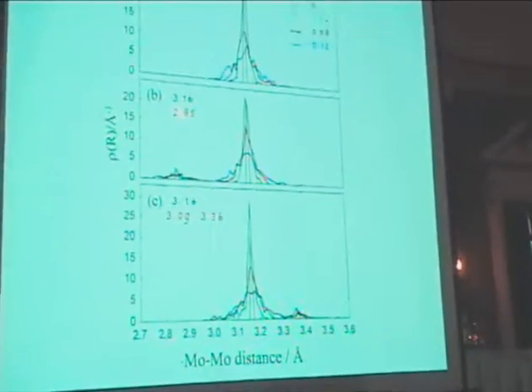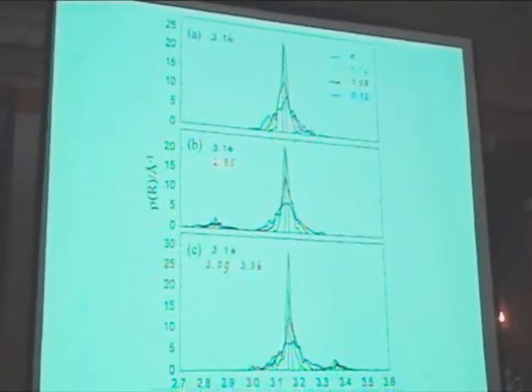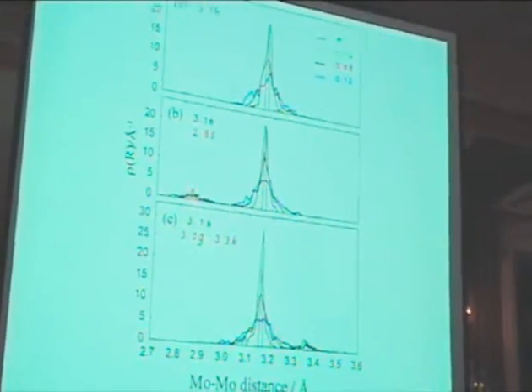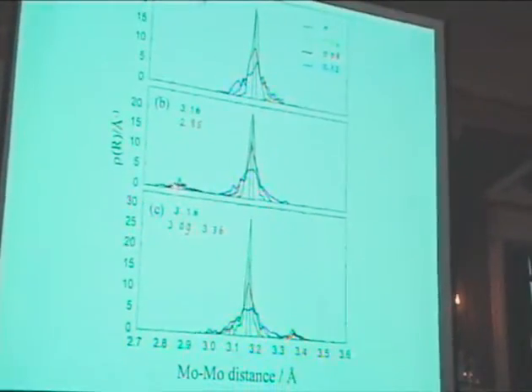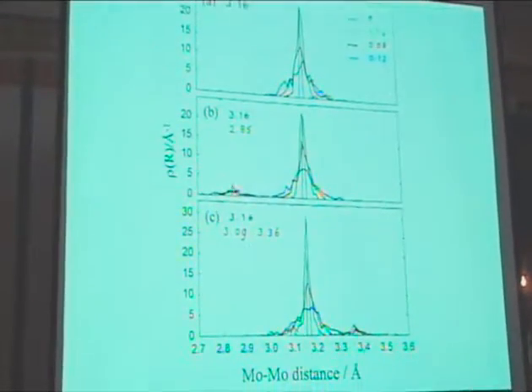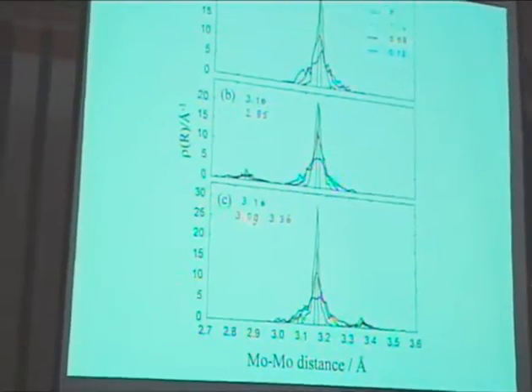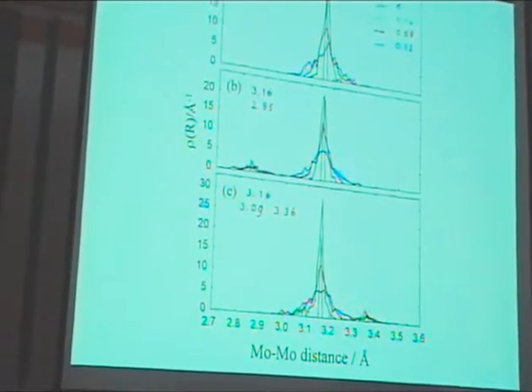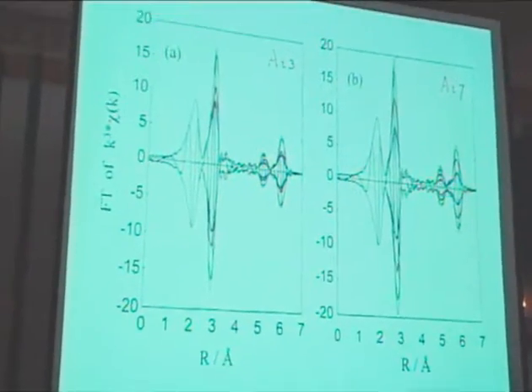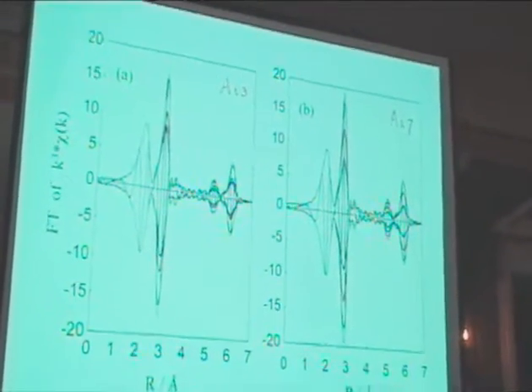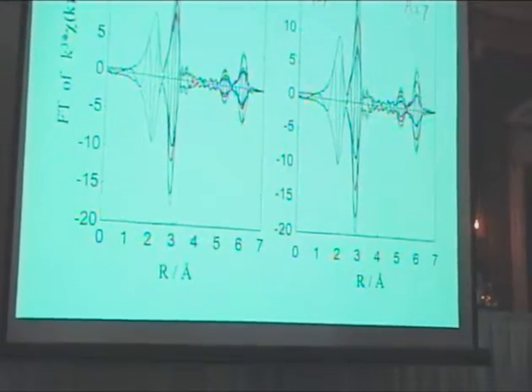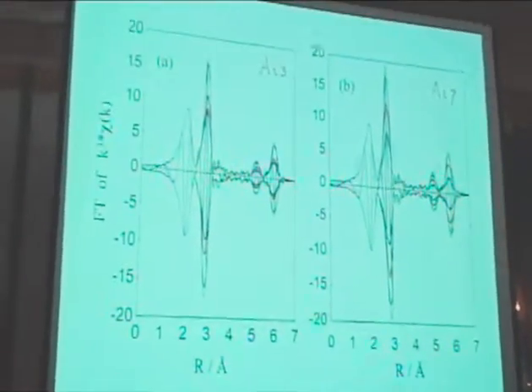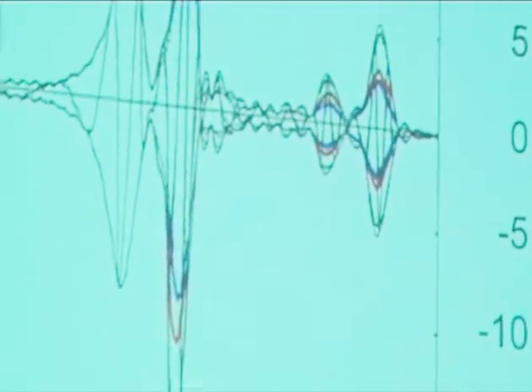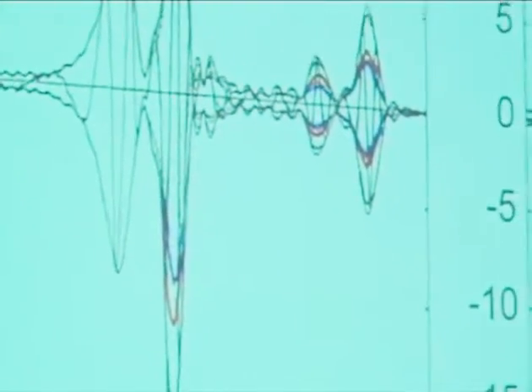Then, because of the DFT calculation, which assumed there was a short distance of 2.85, we tried that. So you get at the edge now a distortion in addition to the freedom. And the third model has a slightly shorter distance and a slightly larger distance. And what we then did, we calculated all the distances, added them up, averaged them, and then analyzed it with the classic EXAFS analysis method, which assumed that everything was having the same distance. And here you see the outcome.